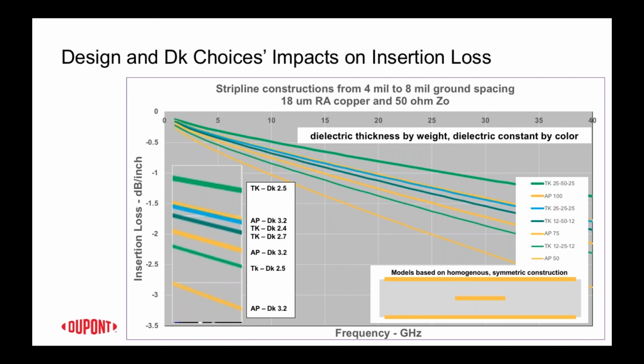And so this establishes some of the trade-offs that could be used for reducing the board height. What's possible is that line widths can be reduced. And in the case of the Pyralux TK at 3 mils versus the Pyralux AP at 4 mils, it's possible to reduce the height while maintaining the insertion loss performance of the greater thickness option.